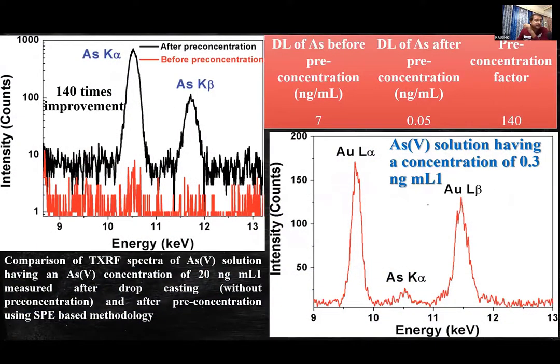You can see that this is the TXRF spectra of a 20 ppb arsenic solution before preconcentration and after preconcentration. In this red spectra, before preconcentration, we hardly see any peak of arsenic. But after this preconcentration, there is a great improvement in the counting statistics. We have also determined the detection limit before and after preconcentration, and there is almost 140 times improvement of detection limit using this methodology.